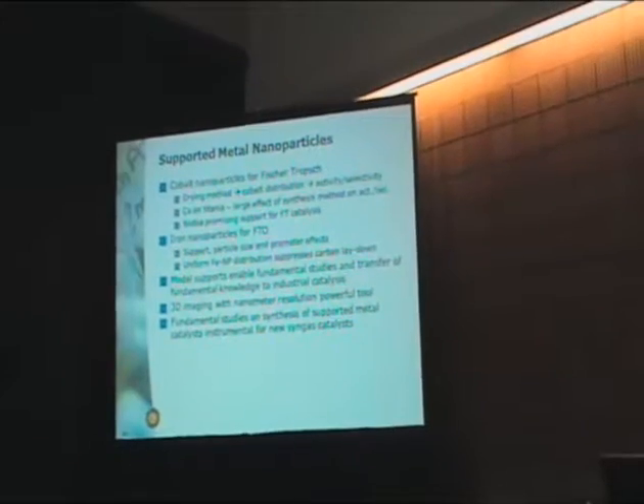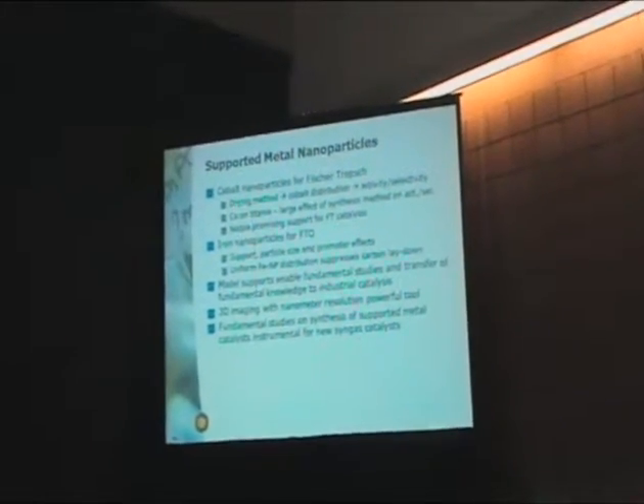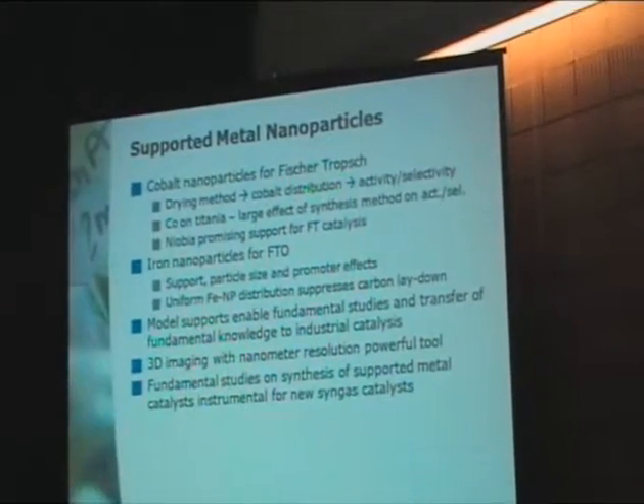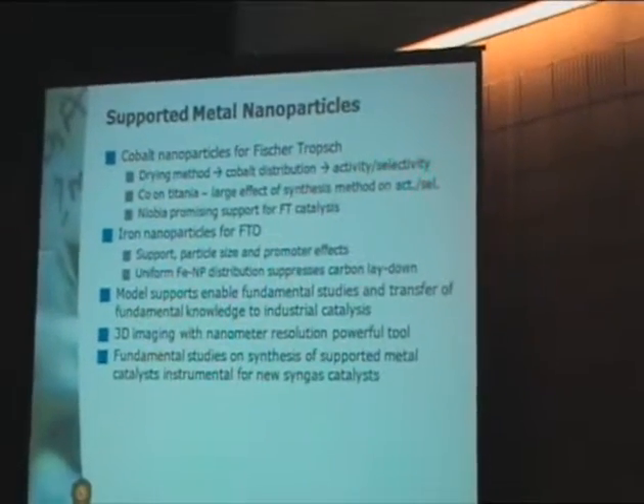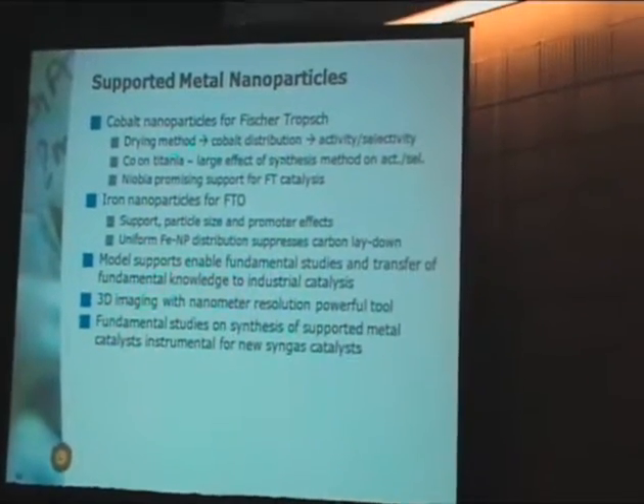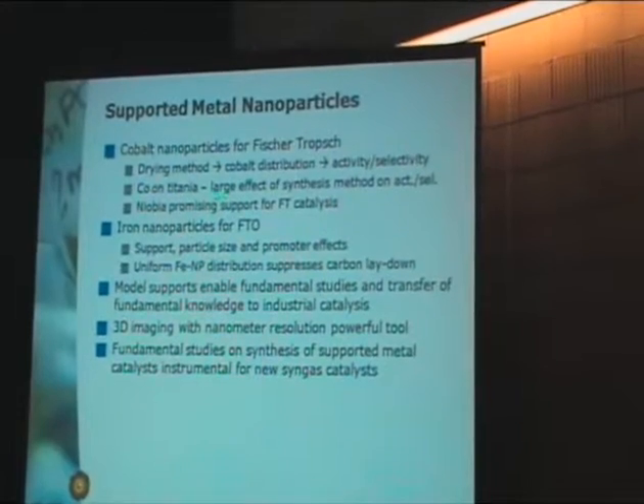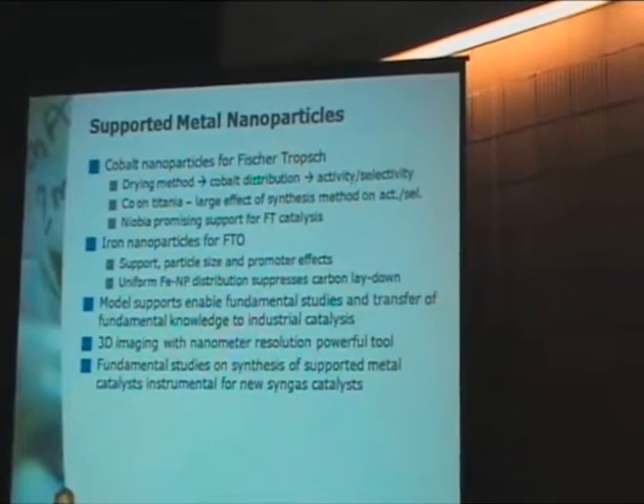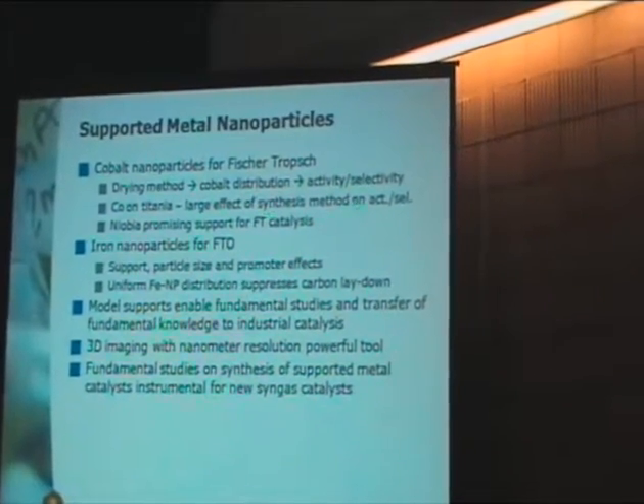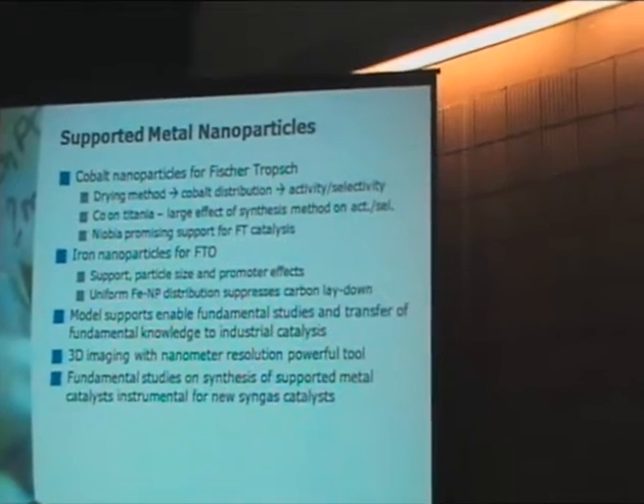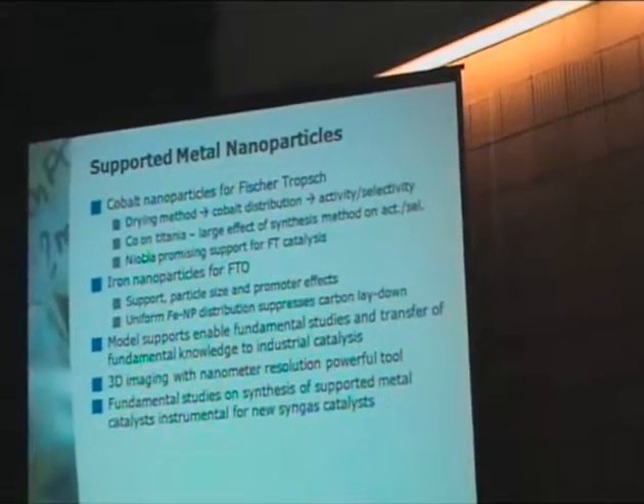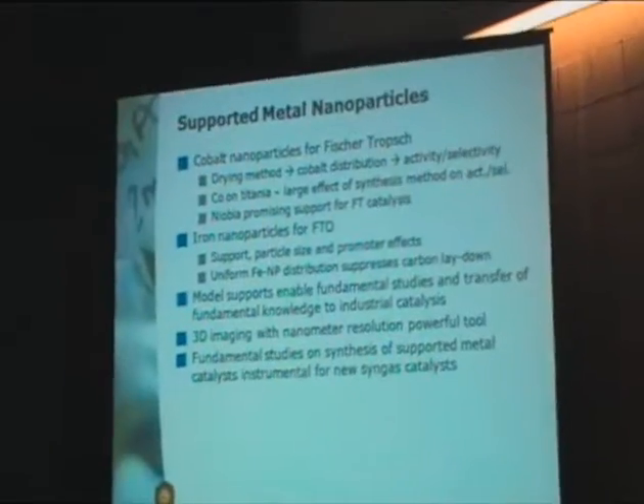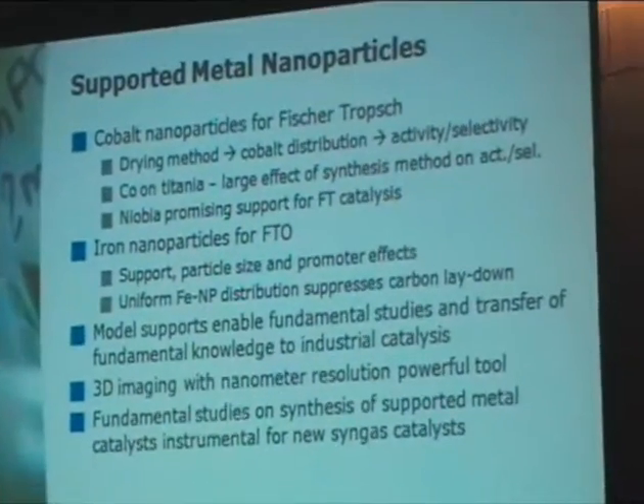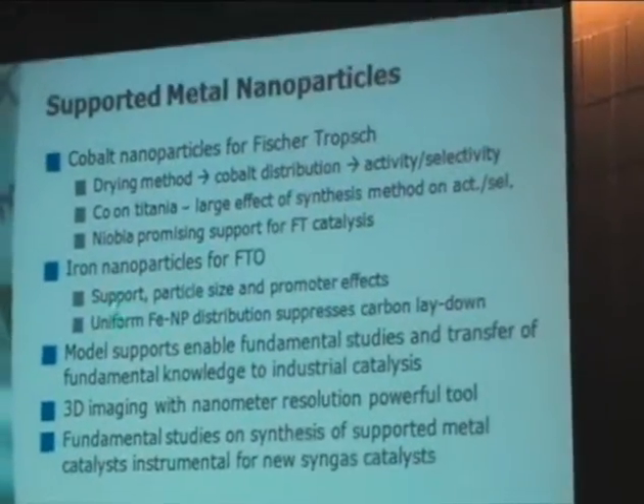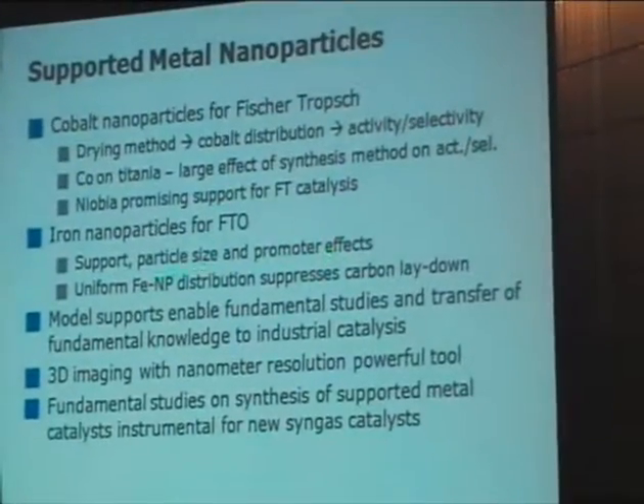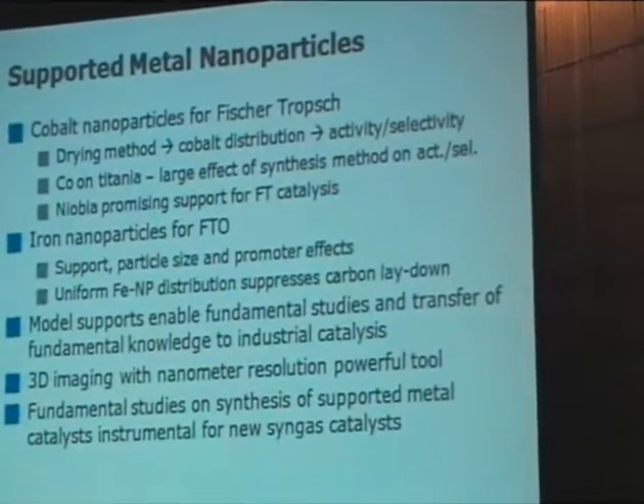So, the cobalt work: the drying method is very important for the cobalt distribution, which affects activity and selectivity, perhaps even stability. Cobalt on titania, we see a tremendous effect of the synthesis method. There's a great surprise, more than what dispersion effects can explain as yet. And niobia seems to be an interesting support to operate, in particular at high temperatures. Iron we discussed: support, size, and promoter effects, and also the distribution of the nanoparticles.